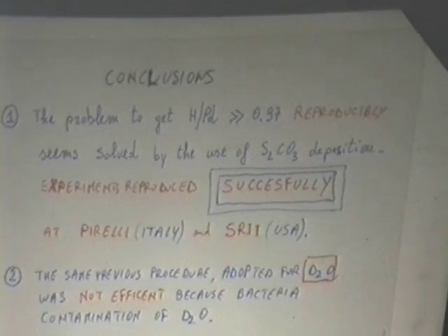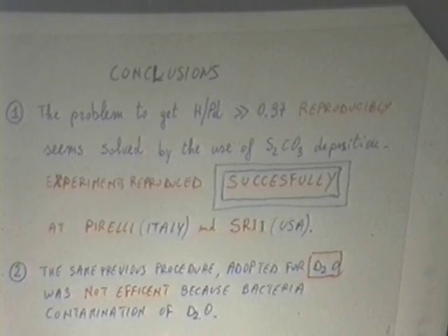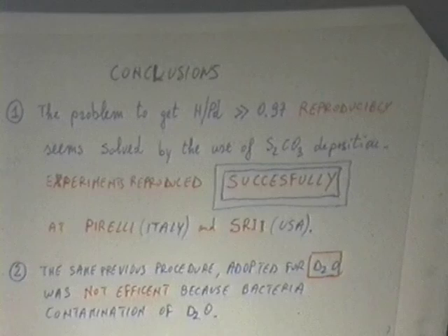So we think about light water, the problem is solved. Our experiment was reproduced at the Pirelli in Italy and the SRI International in the United States. We have problems: the same procedure used for heavy water doesn't work. We have seen that with the proper purified water and the proper circuitry, there is a strong indication of some excess heat, reproducible and controllable. But the problem is that the excess heat is only in some spots.